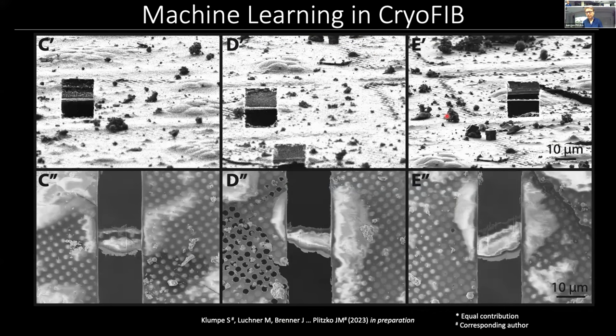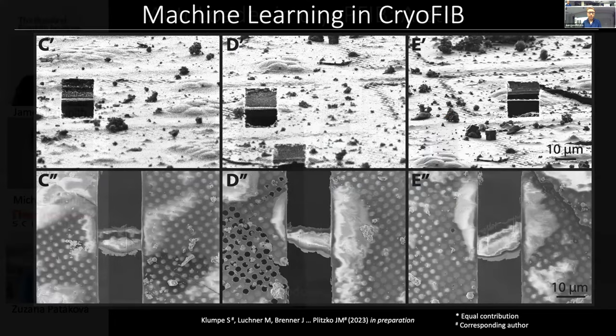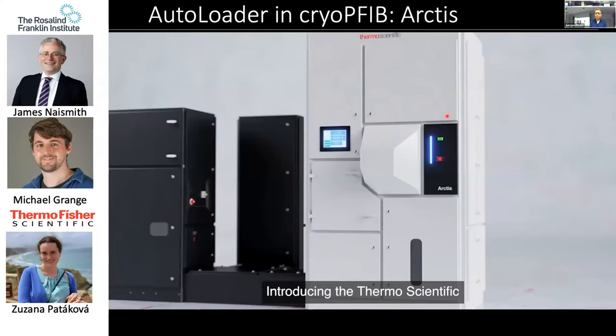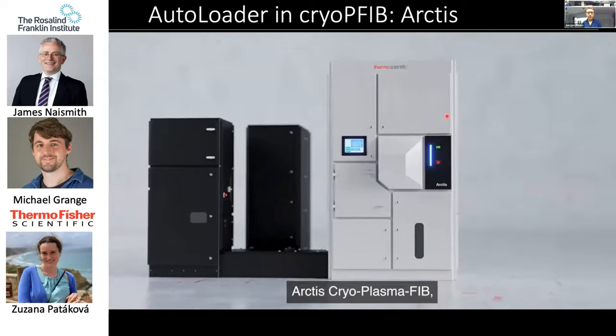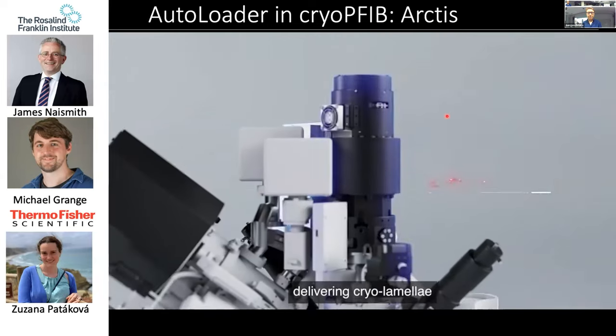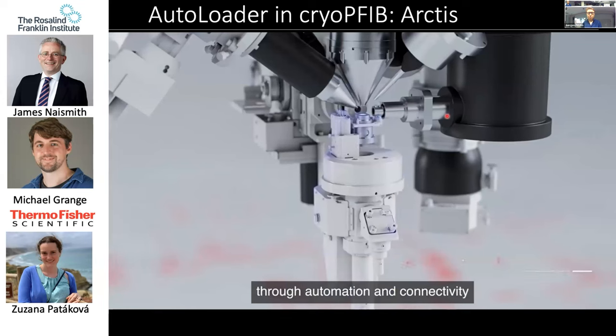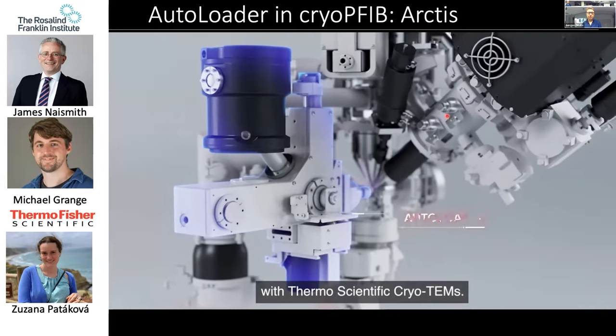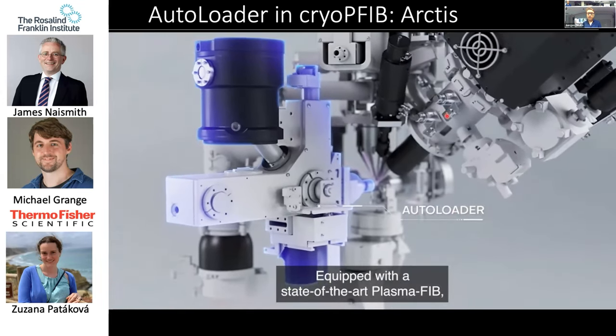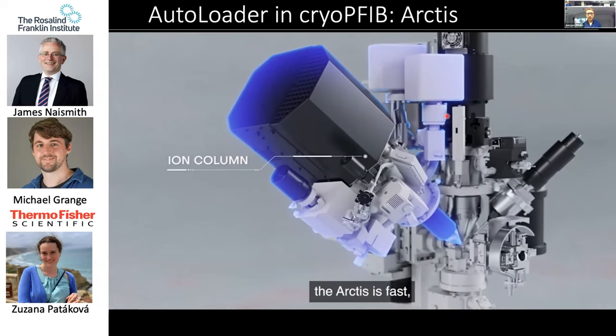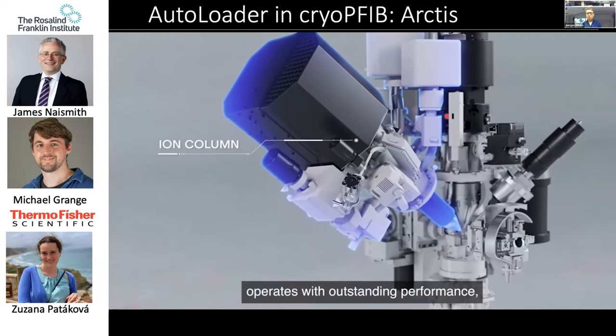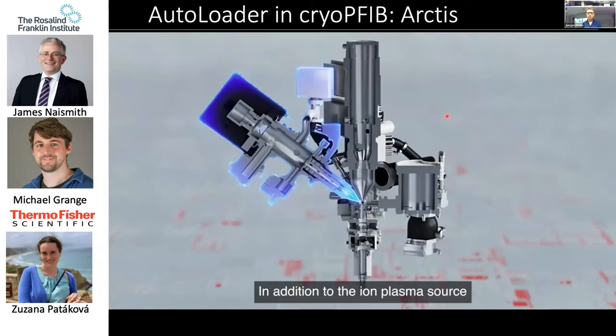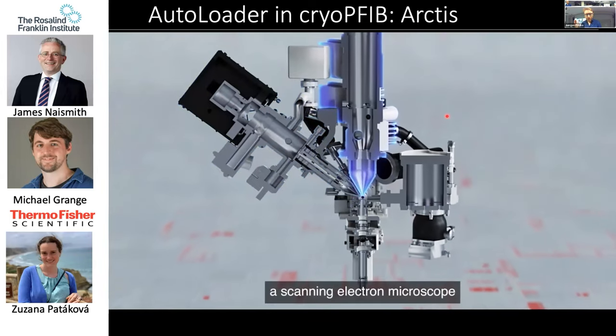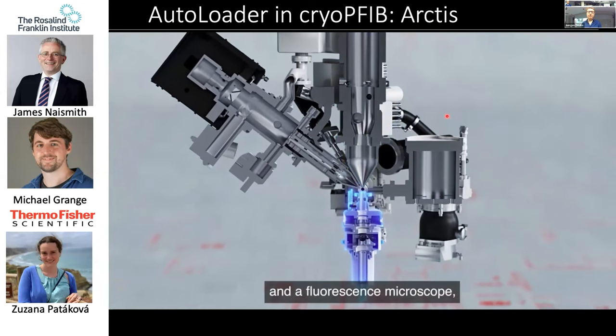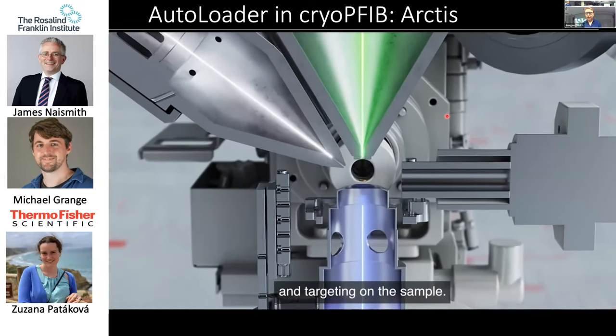But the main development that we still need is to be able to put the sample in and out of the scope automatically. And the Rosalind Franklin Institute, in collaboration with Thermo Fisher, actually came up with the so-called Arctis system, where we have an autoloader combined with an electron column, a fluorescence microscope, and a plasma focused ion beam inside a single instrument. And this allows us really to go through 12 grids with this workflow without any user intervention, and still prepare lamellae of cells inside these 12 grids.